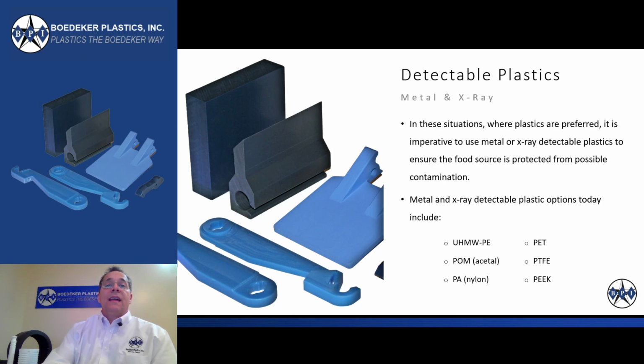Ultra high molecular weight polyethylene, used a lot in these industries today. It's a very tough, very abrasion resistant material, so just great for wear applications. Polyoxymethylene or acetal is a 200-degree material that's very machinable, holds tolerances pretty well, and is another material very common to this industry. Polyamides or nylons are a 200-degree material that really offer unmatched wear performance, just long life in wear applications. PET or polyesters offer improved performance above nylons and acetyls in regard to dimensional stability and chemical resistance.